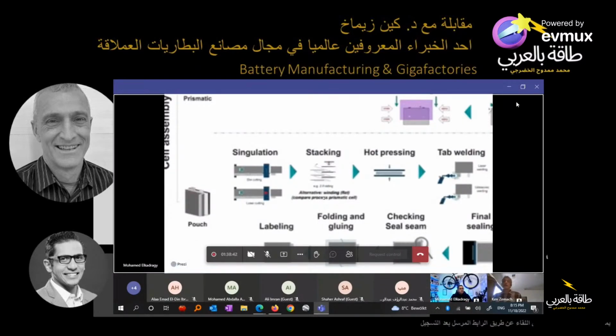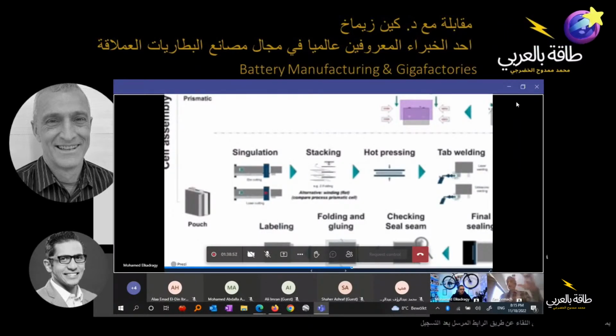So if you take a cylindrical lithium ion cell, and you discharge it, and you get in a fume hood, and you unwrap it, you'll see that the width of the long anode is wider than the width of the cathode. And if you take a prismatic cell, or the sheets, if you were doing singular sheet stacking, the sheets of the anode are wider and longer than the sheets of the cathode. And that is a safety related issue. And you say, okay, great. So when we stack them, we just need to make sure that everything's centered.